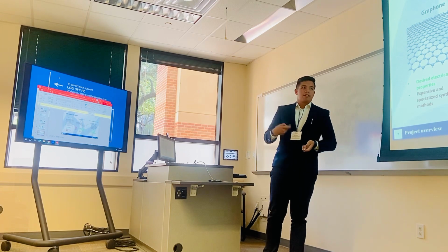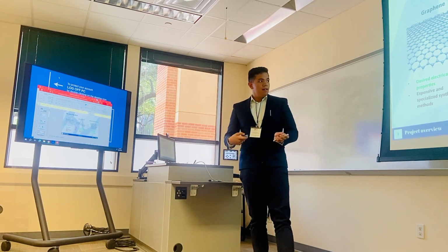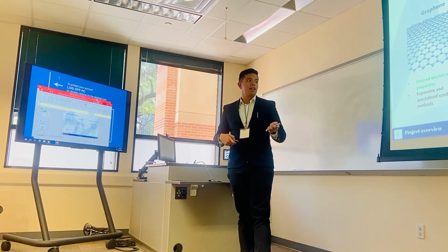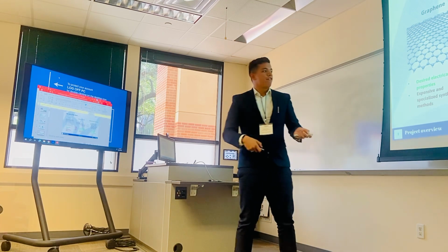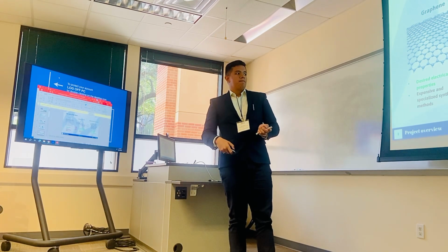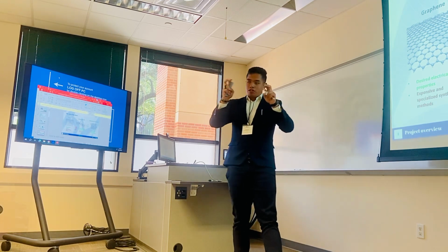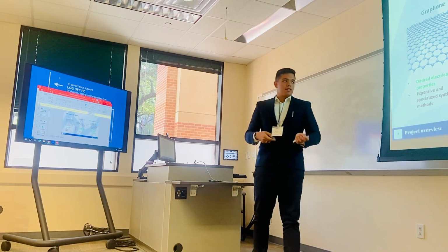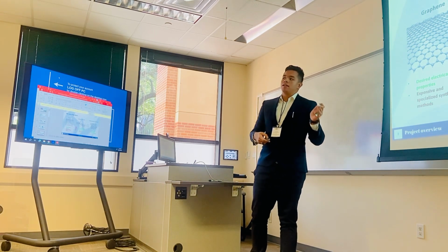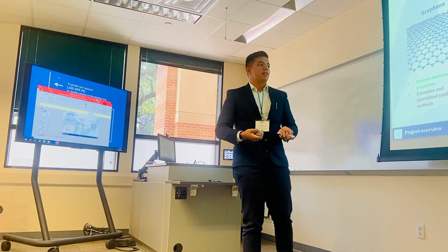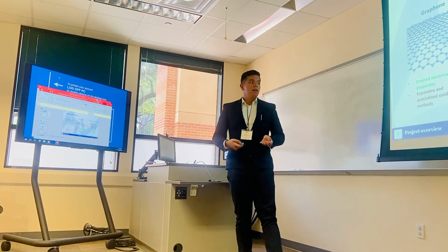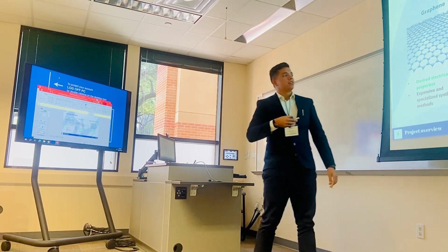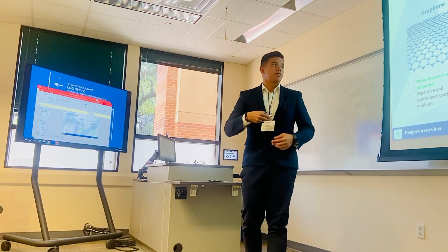There are other variants of graphene. One of interest is graphene oxide, which is not as simple as having oxygen attached to the surface. These are actually a variety of functional groups that are chemically bonded with the surface of graphene. Now this gives us the advantage of accessibility because there's a standardized method called Hummers' method to synthesize this material, which we'll get into. But it loses its electrical properties because the electrons cannot flow freely due to the presence of these chemical functional groups on the surface.